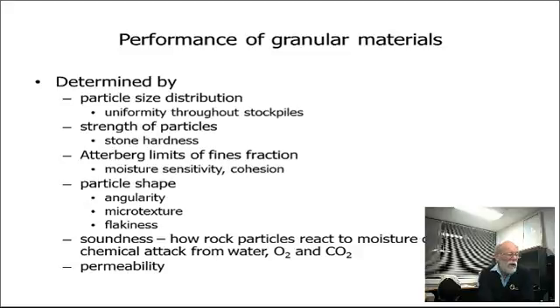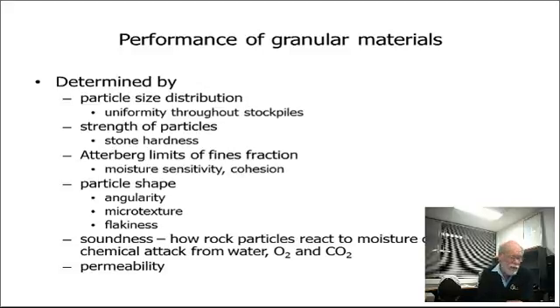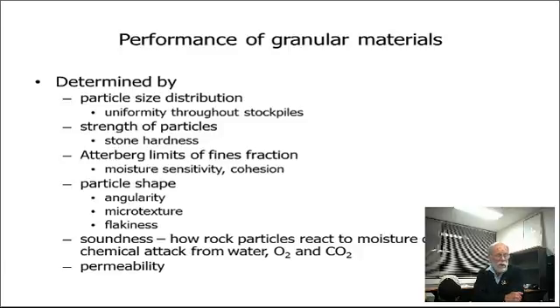Regarding Atterberg limits — some consultants consider that you do need a degree of plasticity to give some cohesion, which is relevant if you're going to put a spray seal on, as it gives a better surface. But others are adamant about why you would put clay into good quality crushed rock. Russell Clayton, for example, refuses to have any PI in a road base. I've found that road bases with PI are far more moisture sensitive than those without.